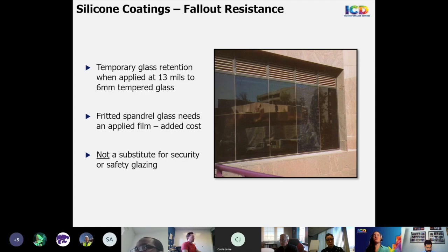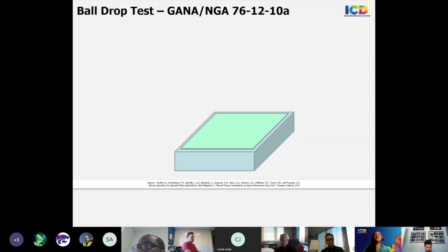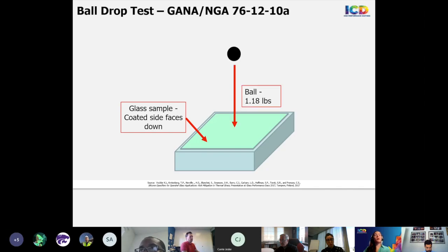This is not a substitute for security or safety glazing. It's its own category, but it could offer an added safety factor to prevent broken or shattered glass from falling from the cavity. So I'm just going to quickly show this ball drop testing because it was tested to determine the fallout resistant effects and impact resistance. So it just used a simple box frame to support the glass. The coated surface is on the underside and in tension when a weighted ball is dropped onto these samples of glass. Then the maximum height achieved before breakage is recorded.